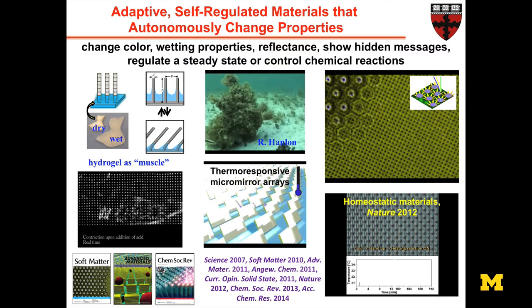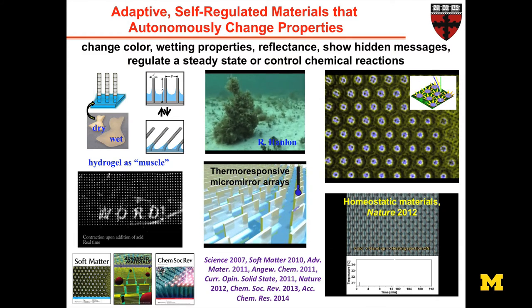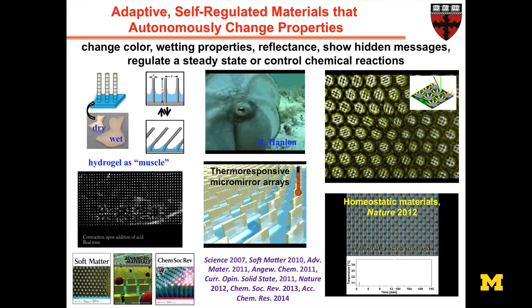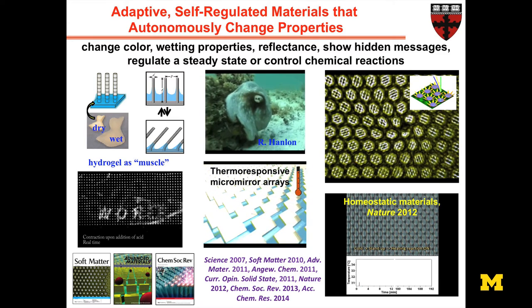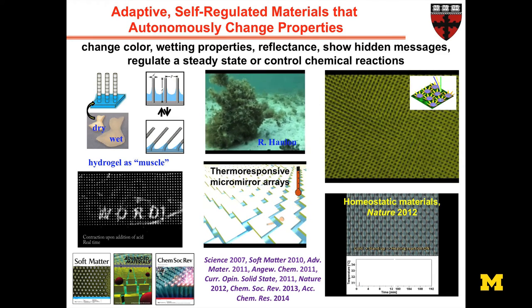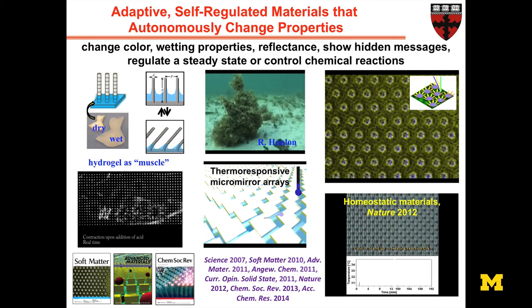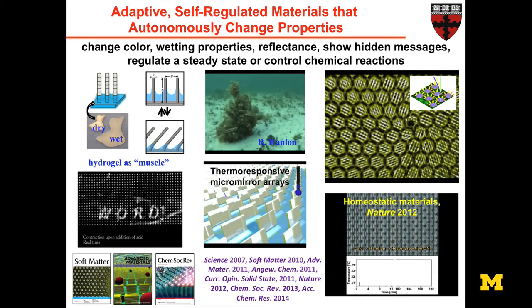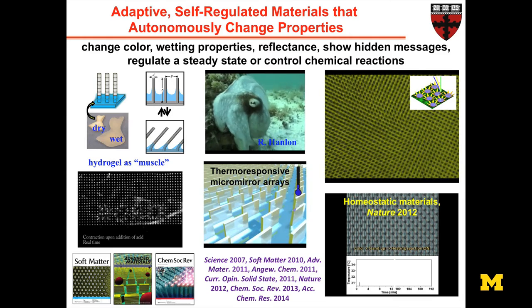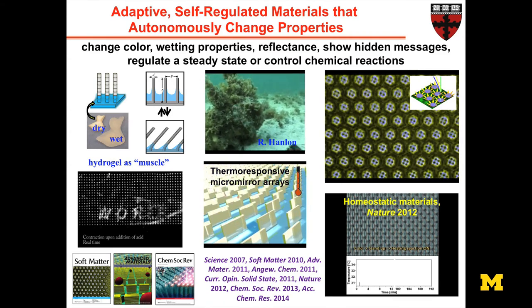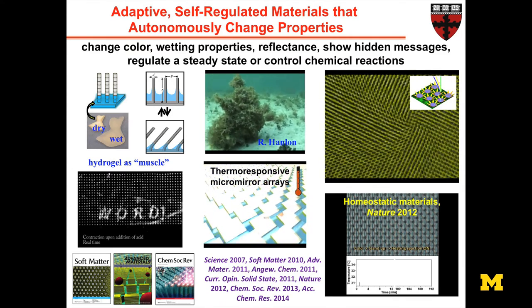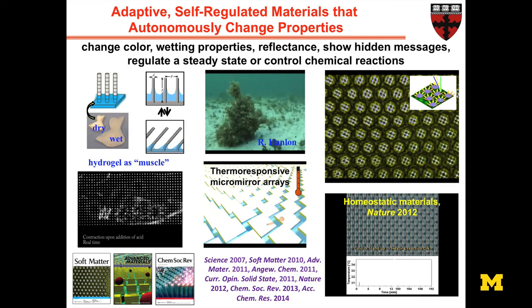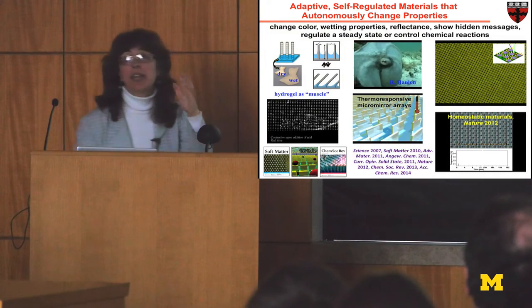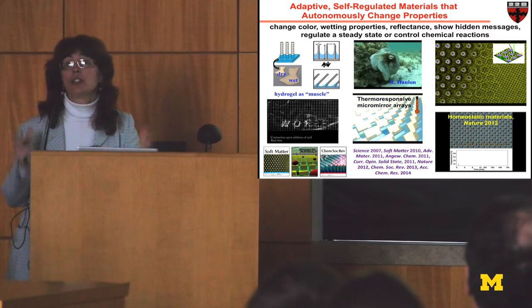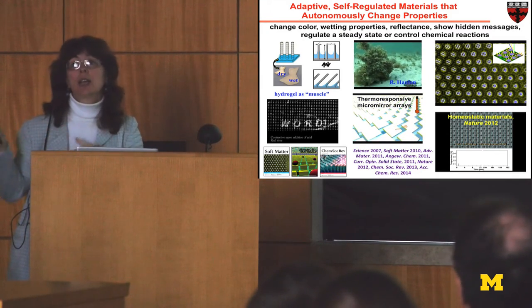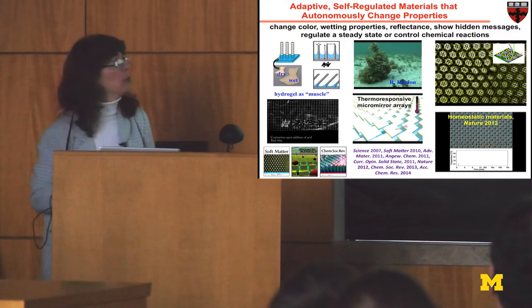One can design the surfaces, and we're doing it now together with the School of Design, where these structures are metallized. They're all at the micron size level, so you don't see them. But when the gel is responsive to temperature, when the temperature is low, they're standing up because the gel is expanding. When the temperature is high, the gel is contracting, and the structures lie down. You don't have to use energy. It responds to the environment outside and becomes reflective as a dynamic window.